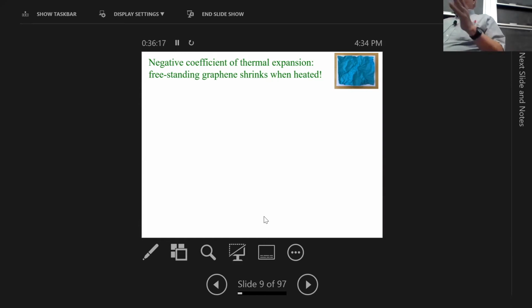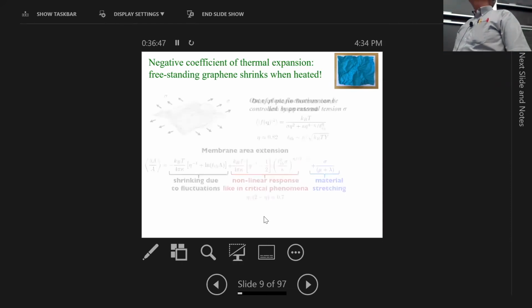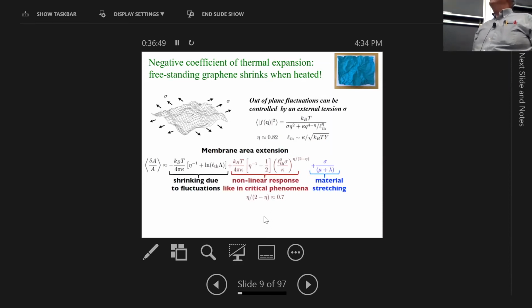And graphene, at least in flat 2D space, is a very stiff material. You might expect it to expand, but you can see that this thing has shrunken compared to the 8.5 by 11 sheet that I started with. And so you can work out the coefficient of thermal expansion. Here the shrinkage is illustrated with this blue wrinkled paper superimposed on a flat white piece of paper. And so in fact, this thing is supposed to shrink when heated.